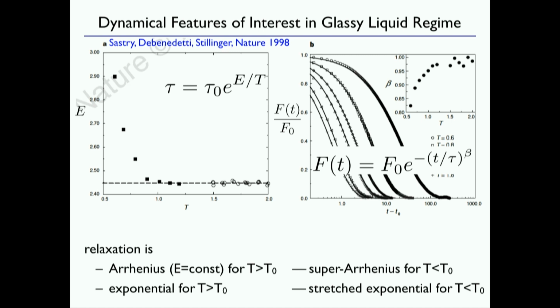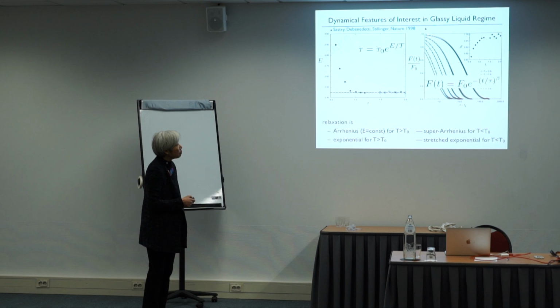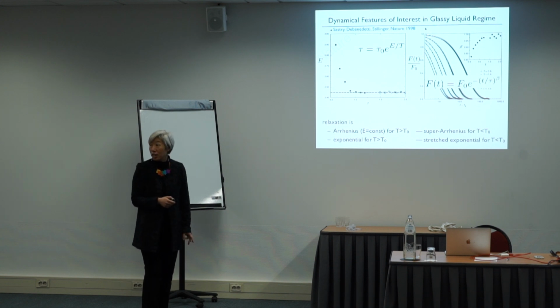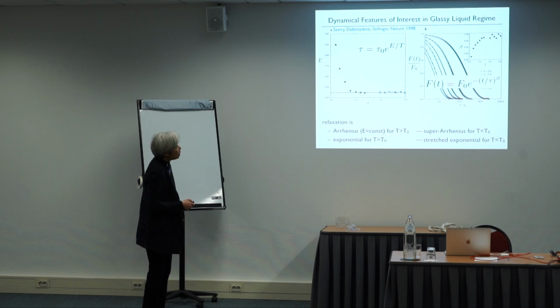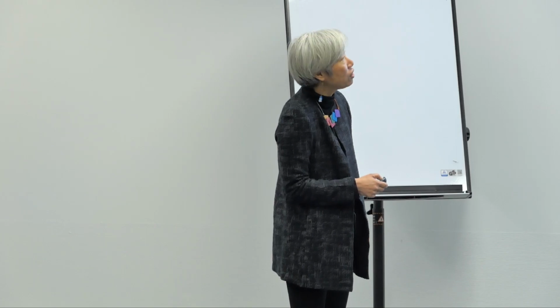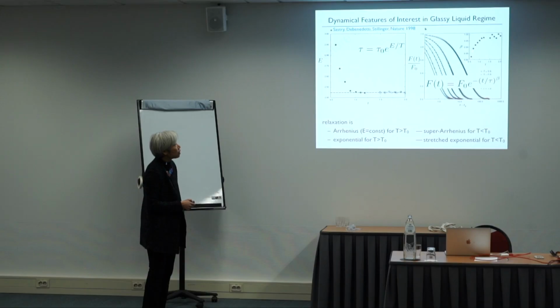So here is, I'm not going to go into what it is, but it decays with time, and it decays on the scale of the relaxation time. And what you see is curves for different temperatures. If you fit it to this form with a stretching exponent, what you see is that at high temperature, that exponent is about 1. It's exponential. But as you go lower in temperature, it drops.